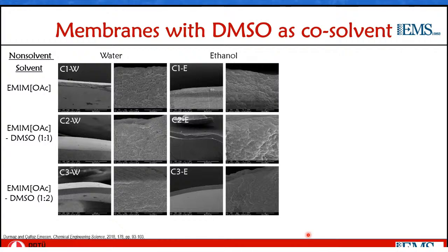Until now, the membranes that I've shown were made with a solvent system that contained mostly the ionic liquid and some acetone, but still the majority of the solvent was the ionic liquid. While ionic liquids are, of course, good solvents for cellulose, when you consider the large-scale application, their price is still quite high. And also their high viscosity, the intrinsically high viscosity of the solvent itself, for one thing, makes the processing a bit difficult. And for a second thing, it changes the phase inversion kinetics into a form that we're not used to with more conventional lower viscosity solvents.